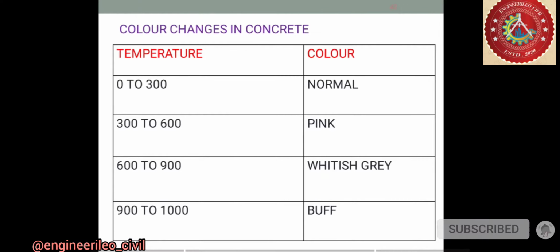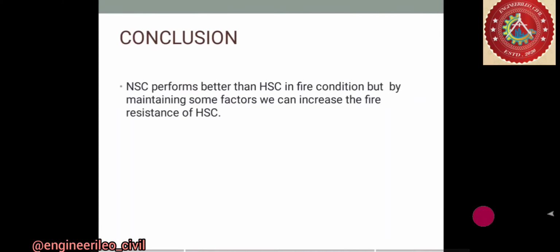And here you can see the color changes in concrete: from 0 to 300 degrees centigrade the color is normal, from 300 to 600 degrees centigrade it's pink, 600 to 900 it's whitish gray, and then it goes to buff. Here you can see the cover requirements or the nominal cover for fire resistance from 0.5 to 4 hours and so on. So finally our conclusion is that normal strength concrete columns perform better than high strength concrete columns in fire conditions, but by maintaining some factors, adding some admixtures, or by tie spacing and other things we can increase the fire resistance of high strength concrete columns.